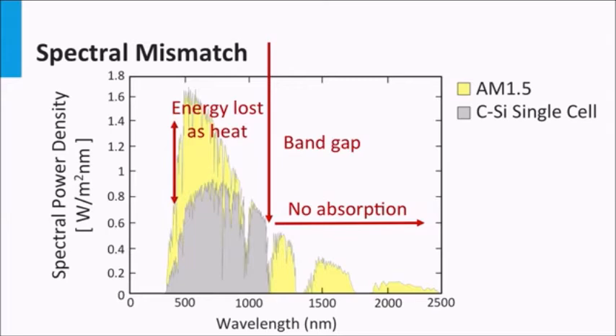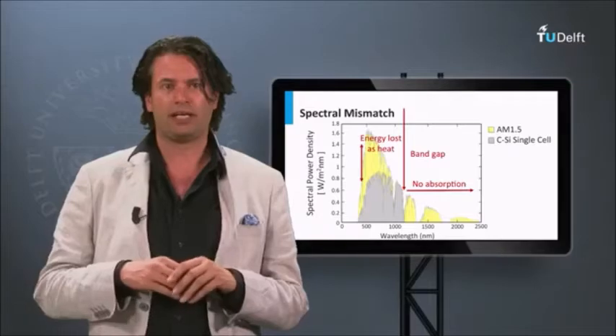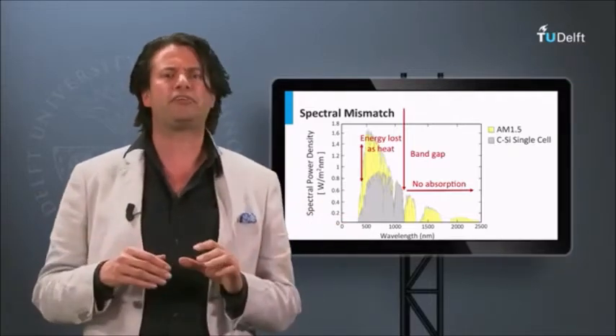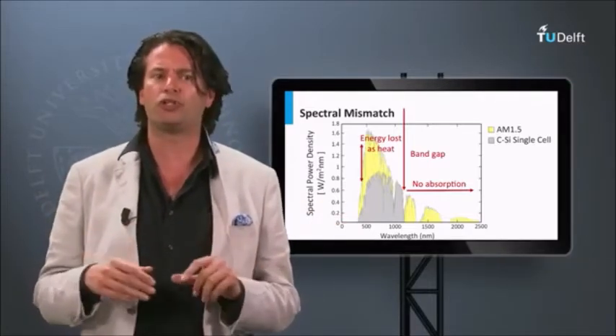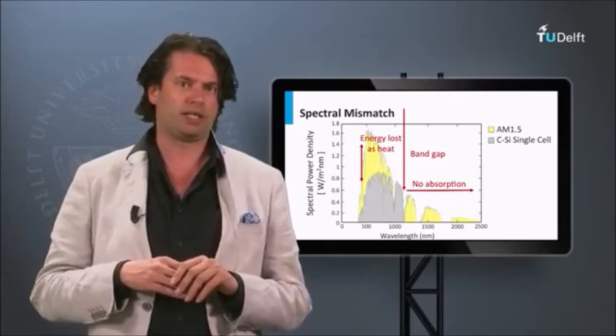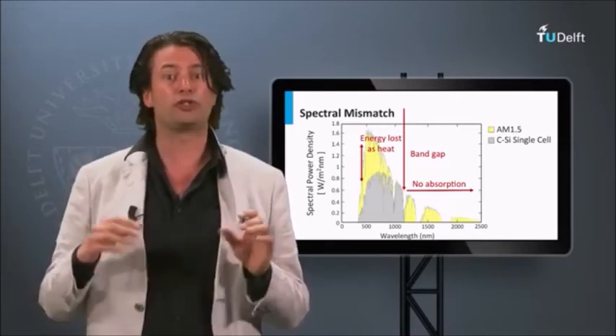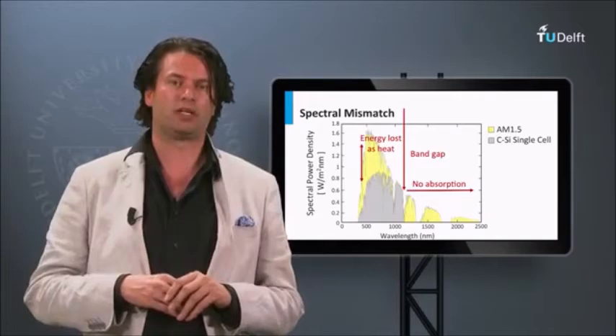The optical losses due to this mismatch between the band gap and the solar spectrum limit the maximum conversion efficiency to 48%. However, this limit is not very realistic. In literature, people generally refer to the so-called Shockley-Queisser limit. This theoretical limit includes two additional loss mechanisms.